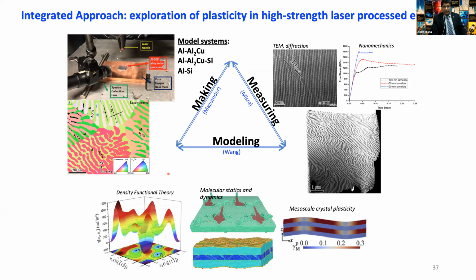In this case, we are picking from phase diagram systems that are eutectics. So eutectic meaning that from a liquid phase, you form two solid phases simultaneously. Aluminum silicon is a very simple textbook example that we teach in undergraduate class. Aluminum copper is another very simple textbook example, very well-known eutectic systems. What if you make it by laser melting, where you get very high cooling rates?